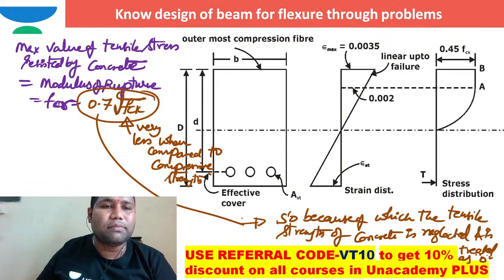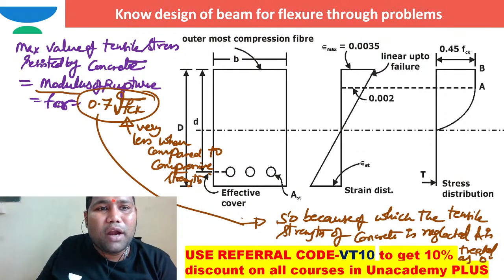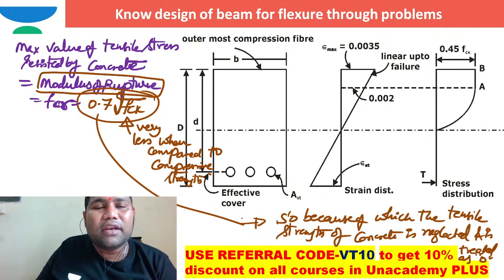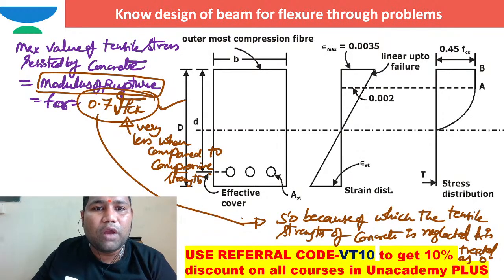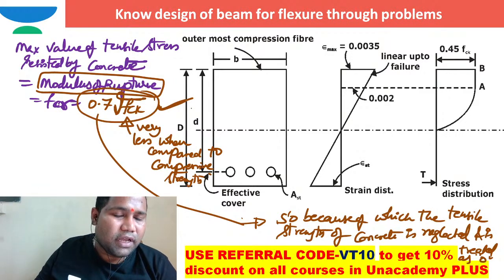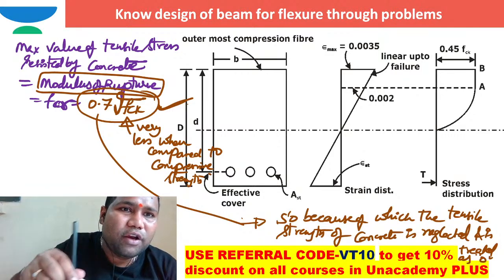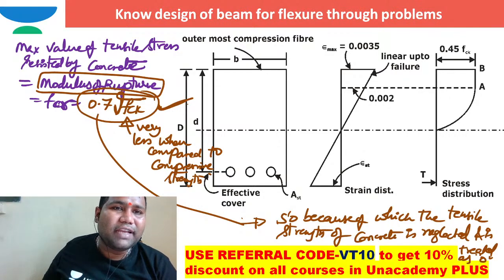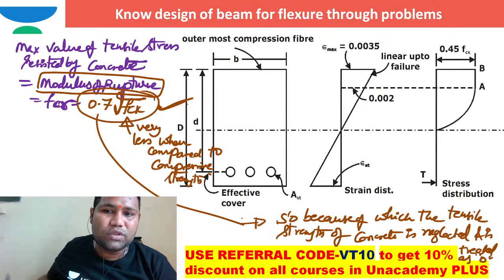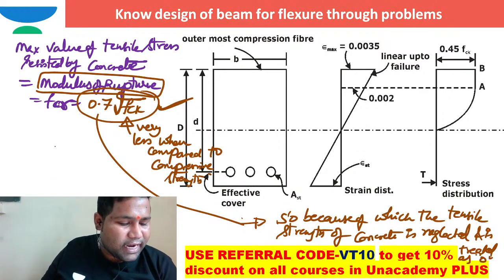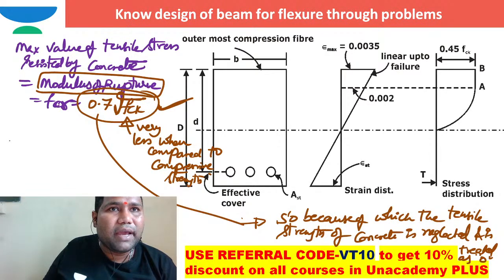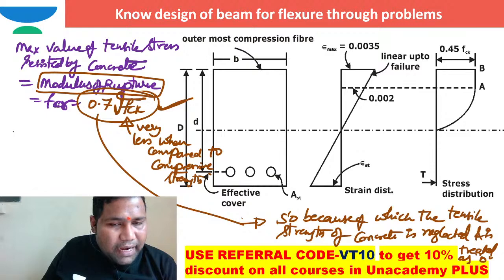Some people will also ask me, sir, how to work out this modulus of rupture in laboratory testing? This is an empirical rule. How to evaluate the modulus of rupture? If I want to work out the actual value of modulus of rupture, the flexural tensile strength of concrete, I hope you know, you take a prism of dimension 150 by 150 by 700 and apply a bending test.